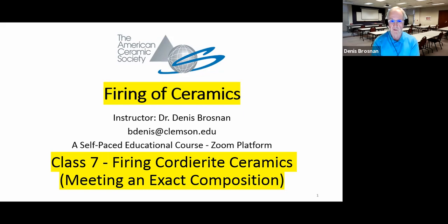Okay, if you didn't like that information, then you just really basically needed to learn that there are reasons internal to the material that we need to slow down during parts of sintering and need to avoid too much liquid formation. As you'll see in firing cordierite, you form a liquid pretty darn quick when you get up to the sintering temperatures, so you have to be very careful. So cordierite's a lot different material to make.